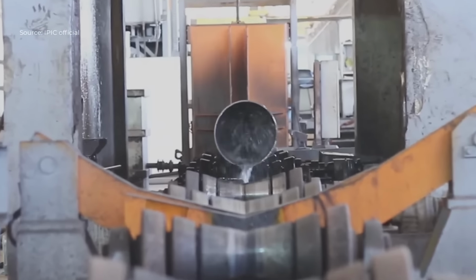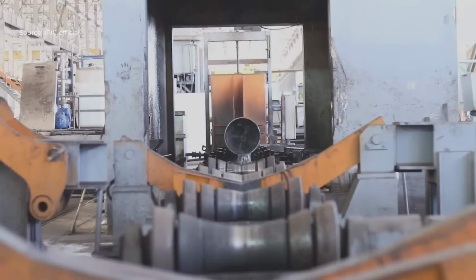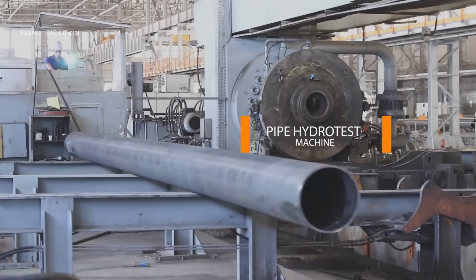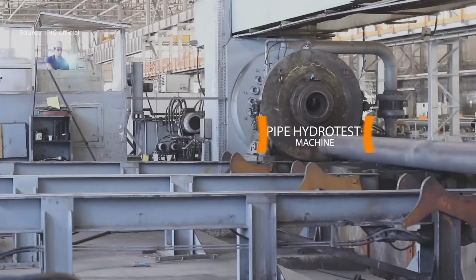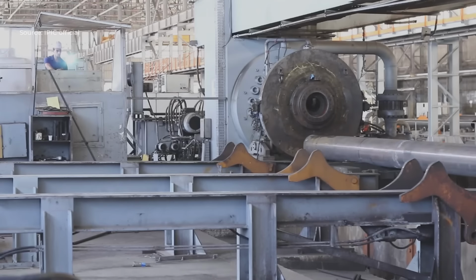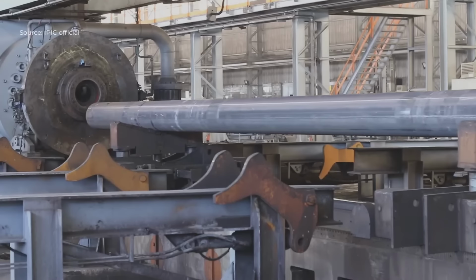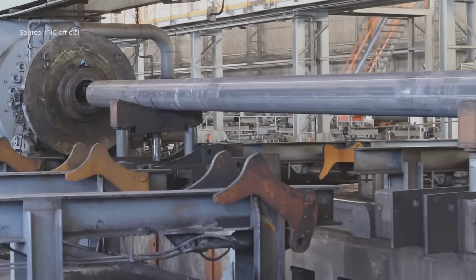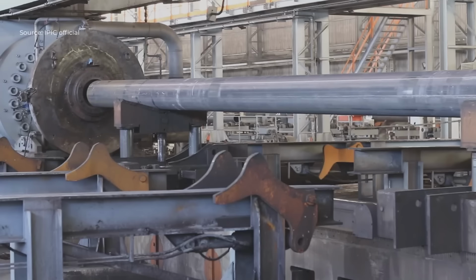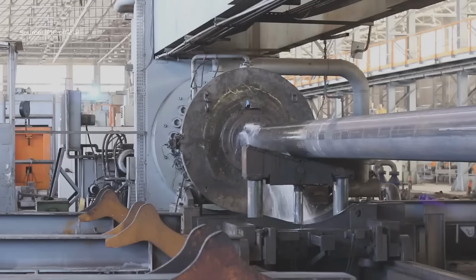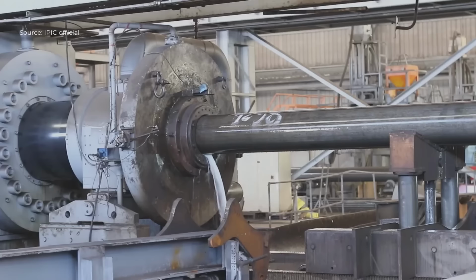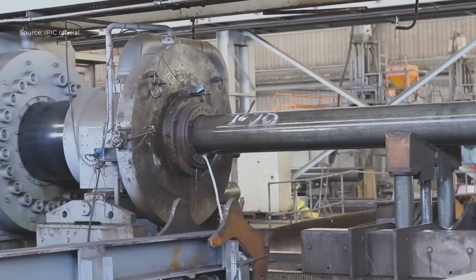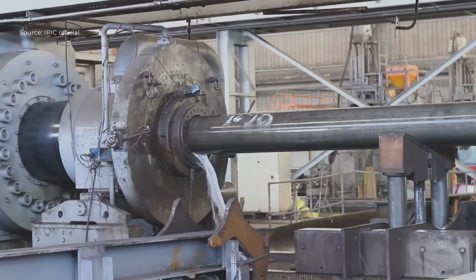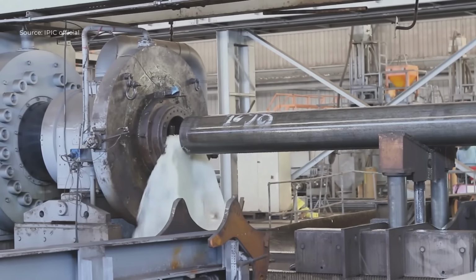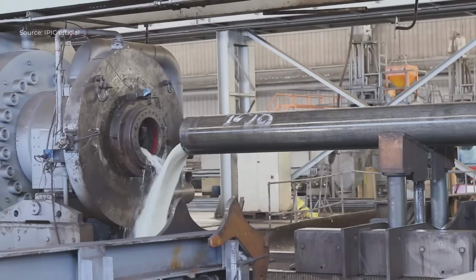Next, the pipe enters the expander. In this step, mechanical or hydraulic expansion is applied to bring the pipe to its final diameter and roundness. The expansion process also helps release residual stresses induced during welding and forming, improving the dimensional accuracy and structural integrity of the pipe. After expansion, the pipe passes through the post-washing machine, where it is thoroughly cleaned again to remove any residues or contaminants left from the expansion process.